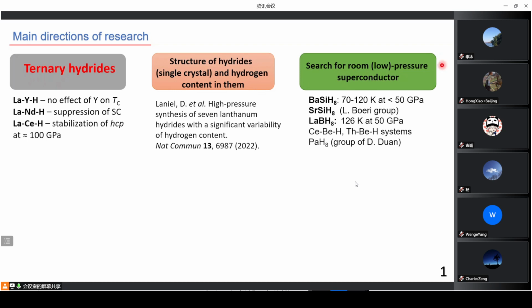I would like to say here that these first 2 compounds are much simpler to synthesize and investigate, because a precursor for those hydrides can be synthesized at low pressure, at 0 GPa, because barium silicide and strontium silicide, with exact one-to-one stoichiometry, were already described. They were already synthesized, and we can just repeat this synthesis, mix barium with silicon, heat the mixture, and get the precursor for consequent loading of hydrogen using, let's say, ammonia borane. Heat barium silicide together with ammonia borane, and maybe we will be able to synthesize this barium silicide H8 (BaSiH8) or strontium silicon H8.